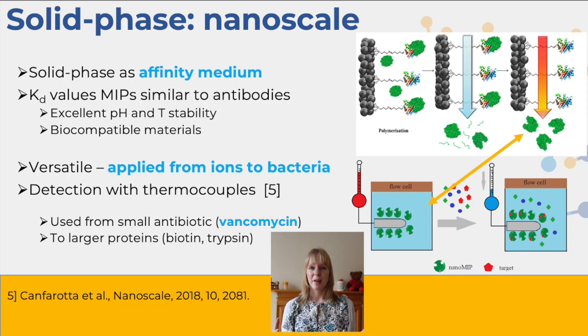When you use that solid phase, you can separate homogeneous particles with the high affinity that you want. Also, a big advantage when you work with nanoparticles is that they can become soluble in water and they are biocompatible, unlike the big microparticles. So you could start to think of other applications. So what we've done, we looked at a range of compounds, and important for this particular topic, we looked at some antibiotics, including vancomycin, and developed materials for that.